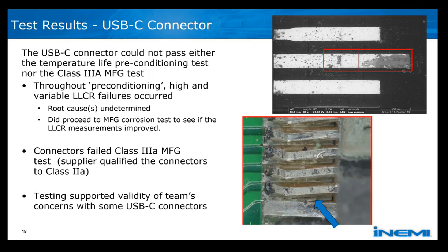We were surprised that we couldn't really identify anything, but we couldn't find a demonstrable root cause right after the temp life. As we continued testing and completed the mixed flowing gas corrosion testing, we were seeing a very high number of contacts failed, kind of hitting the wall, as Phil said, after the first pass through the gas corrosion testing. We stopped the test, we pulled more samples for analysis, and the photographs on the right show examples of two things we particularly noticed.